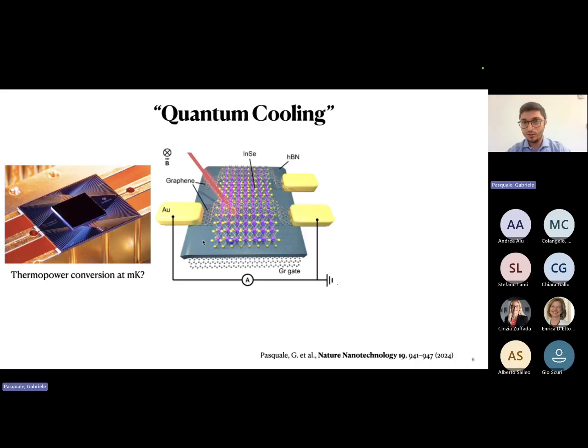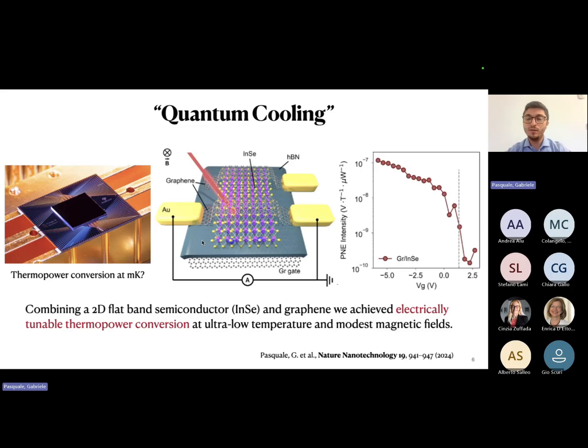During my PhD, I did some research on exactly this topic, where we combined the two-dimensional semiconductor indium selenide with graphene, and we built a thermoelectric device, which basically does thermopower conversion under magnetic field. What we have seen is that the thermopower, so the efficiency of conversion, can be controlled by gate voltage and can be increased by 3 orders of magnitude electrically, some sort of transistor, if you wish. What this means is that we can control locally with a nanoscale device how we translate heat into currents and vice versa.